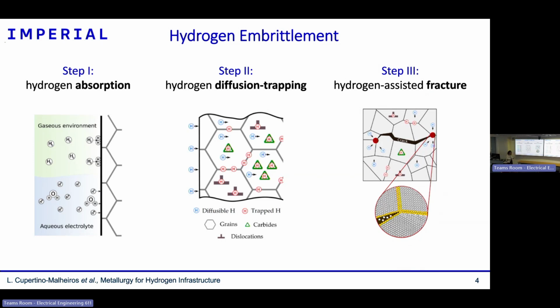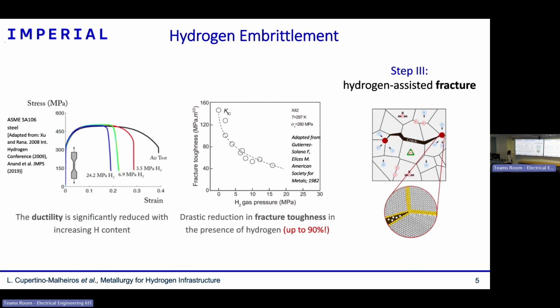Okay, but how serious is this? So is hydrogen really modifying that much the fracture behavior of alloys? And the answer is yes. And you can see here in these two graphs, the first one here is a stress strain curve. And if you have never seen that before, it's basically a test where you take a bar or a plate and you pull it. And what you are showing here is the stress, proportional to force, and elongation. So these are four tests done for the same steel material. And the only difference here is that for some of these tests, the sample was tested in air and for others with hydrogen.